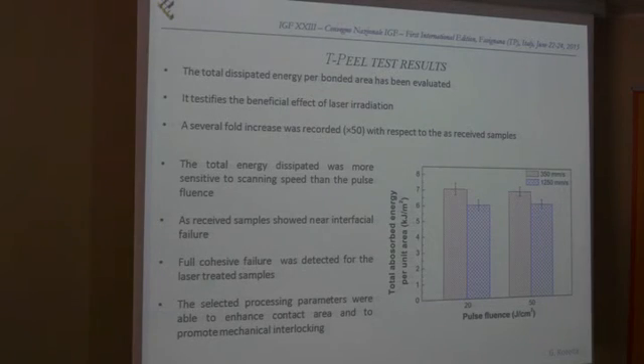And the result, okay, here the as received is not reported, just because it was 50 times lower than the worst laser-treated sample. So basically, we were able to increase the strength of the joint. And as you can see, once again, we confirmed the previous results, saying that the pulse fluence did not have a huge influence, but the process itself was driven by the scanning speed.